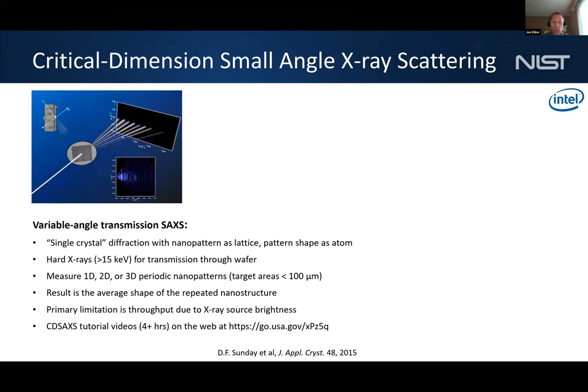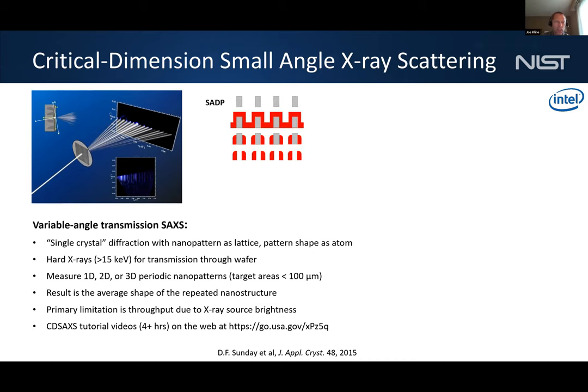And the most important part is it has to be a periodic structure. And so you can measure 1D, 2D, or even 3D periodic structures. And then the other important aspect is that the result is the average shape of this repeated nanostructure. And so this is actually very valuable for the semiconductor industry when they're doing process control, because they want to get really good statistics. If you only look at, say, one FinFET structure, that doesn't tell you very much about the other billion that you have. And so that's where it's very important and critical to have this good statistical sampling.